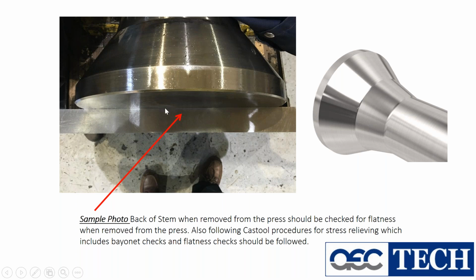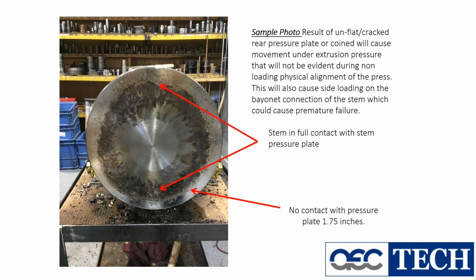Now this is a sample photo that I took in the plant, and this is the flatness of the back of the stem. We had a customer that was breaking some stems and breaking some dummy blocks. So of course, you know, we start looking at everything. Once we pulled the stem off, we found that the outside 1 3/4 inches of this back of the stem was not making any contact with the pressure plate.